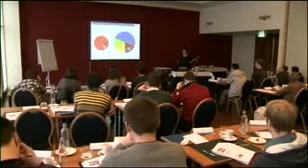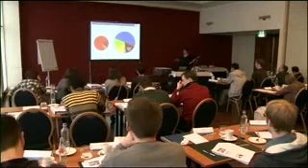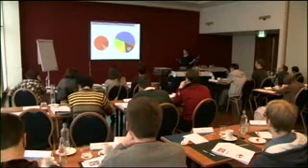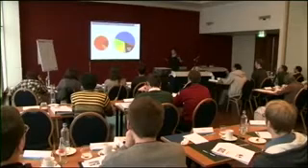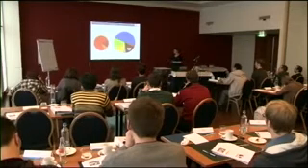So now let's go from the cement powder. And the cement powder, as I told you before, is about 70% C3S. In this example, 15% C2S, 8% C3A, 7% ferrite. That would be pretty typical proportions for a Portland cement. And this reacts with water. There's an increase in volume. That's proportional to the increase in volume here. And at the end, this says for a 14 months paste. You can assume that's kind of a mature state of things.